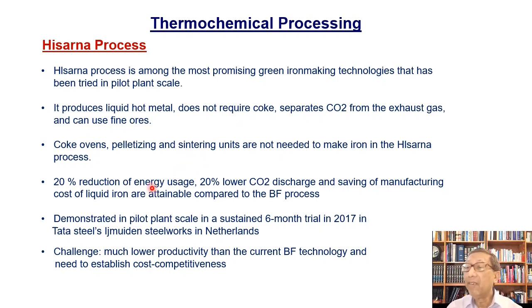A 20% reduction of energy usage, 20% lower CO2 discharge, and saving of manufacturing cost of liquid iron are attainable compared to the blast furnace process. So this is a big improvement if they can be deployed. This was demonstrated in a pilot plant and sustained for 6 months of trial in 2017 in the Netherlands, in Tata Steel's plant. The challenge here is much lower productivity than the current blast furnace technology and the need to establish its cost competitiveness. The secret is that clean steel is going to cost a little more, and we need to pay for cleaning of the steel.